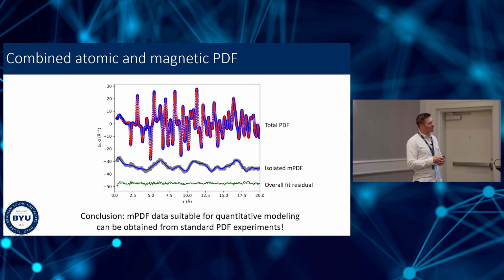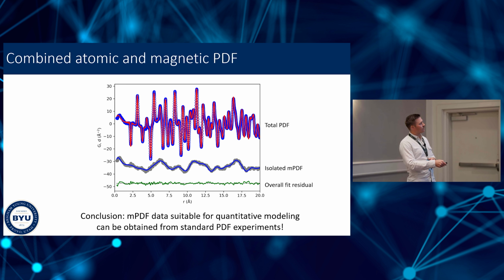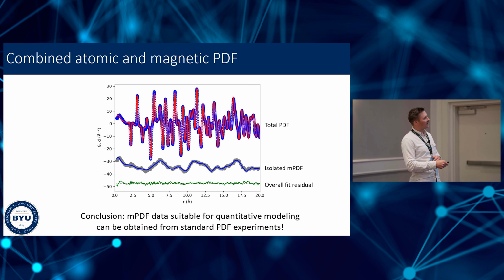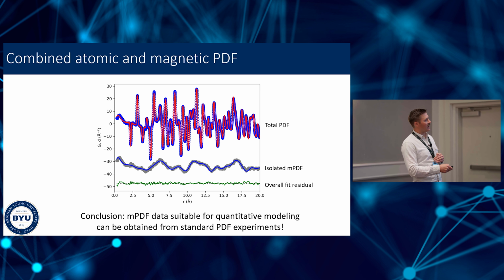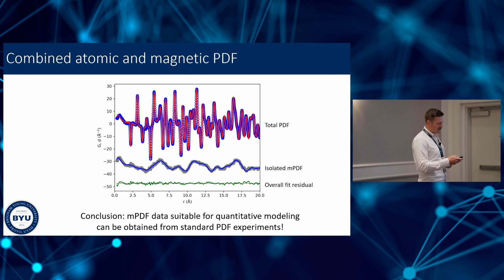But what was more interesting was looking above the Néel temperature, where there is no long-range magnetic structure, but there are nevertheless short-range correlations. Oh, let me explain this first. So often we'll show magnetic PDF data in the form here, where we have our total PDF signal and our total PDF fit. That includes both the nuclear and magnetic PDF up here. And then this is just the isolated magnetic component right here. Okay? So this is the magnetic PDF part of our overall signal. And then this is the overall fit residual. So it worked. Very, very good.